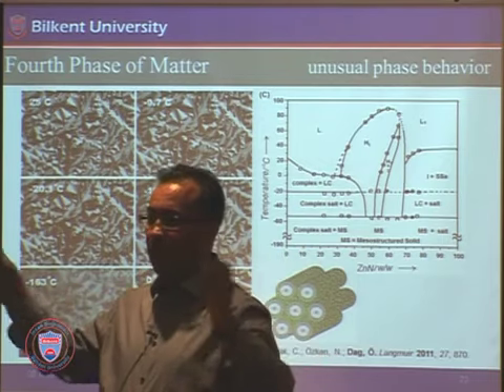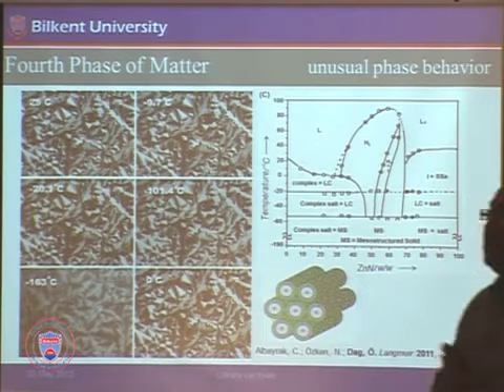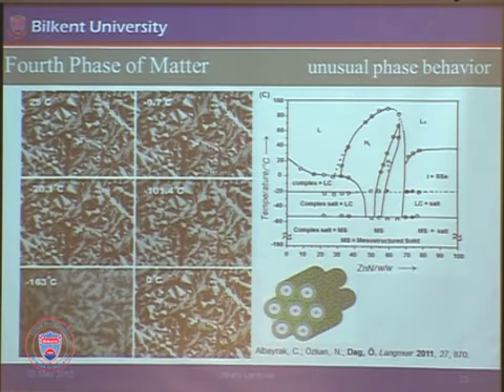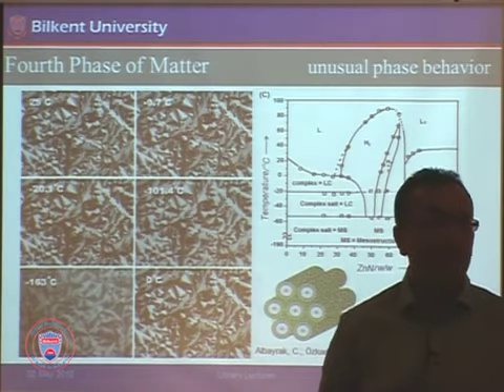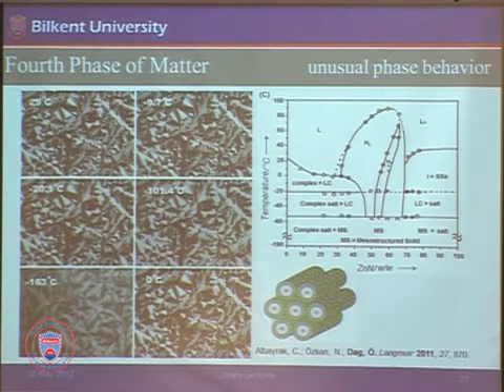Bulk materials, anything we see, is larger than a micron. But a micron is 1,000 times larger than these nanometers. As a result, if you put those in, they go into the liquid phase. And we discovered that those salt ions are liquid and organized with the surfactant into these liquid crystalline phases. Then we realized, oh, these solvents may behave completely differently than water molecules, so under the microscope we started heating. This is 25 degrees.